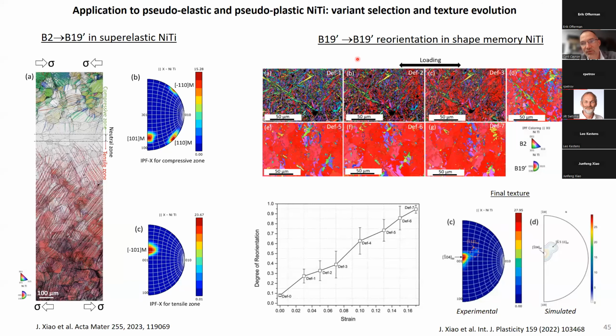We can do that also for another type of shape memory alloy, in which initially it was not austenite, it was already martensite. And when we apply a tensile test, we have what is called variant reorientation due to the tensile test. And we start with laths, and progressively they become blocks. And you see, initially we have a lot of colors, a lot of orientations, and at the end we have only one unique color. It means that we have formed one unique orientation. It is called variant reorientation. And during variant reorientation, here it's the degree of variant reorientation, and here it's the strain. And it fits very well with what we can predict by the interaction work. Here it's an example of the experimental pole figure and the calculated, simulated pole figure.